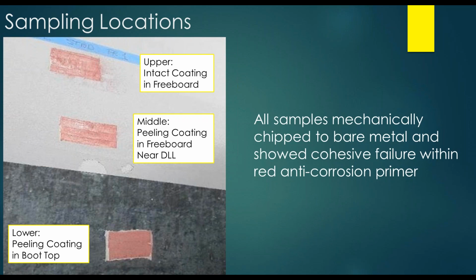These samples were mechanically chipped to bare metal, and the red that you're seeing in these areas is actually a cohesive failure within the red anti-corrosion primer. It should be noted that lots of the samples were readily available by just removing them by hand because they had already started to peel.